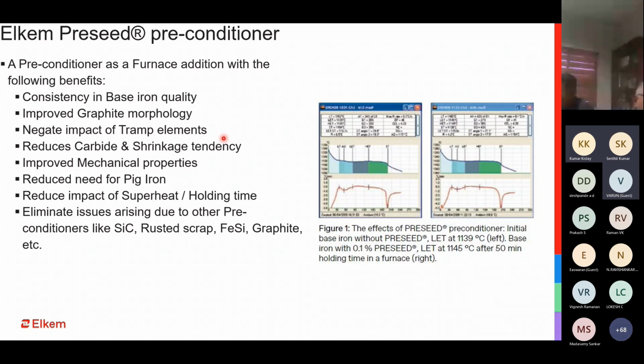When you add silicon carbide, you end up with inclusions. When you add rusted scrap, you do not know how much to add, or you may have to add a lot. When you add ferrosilicon, you do not know how much calcium content it has. So that means we are not sure how effective it would be. There will be a limitation on the graphite that you are adding. So all these negative aspects can be controlled when you have a preconditioner, more like a pre-seed.